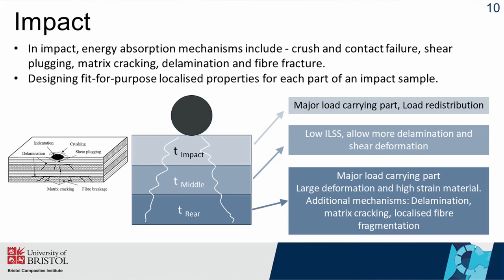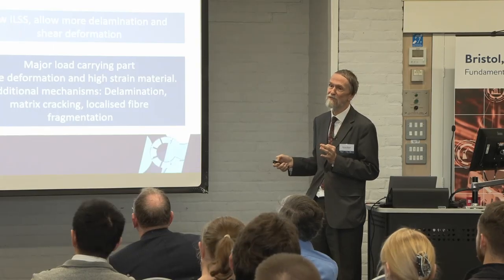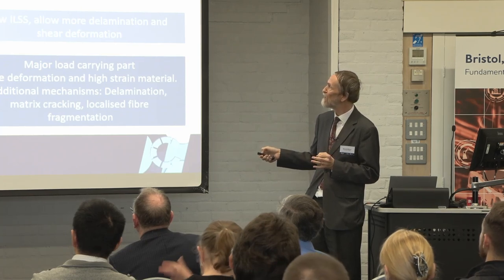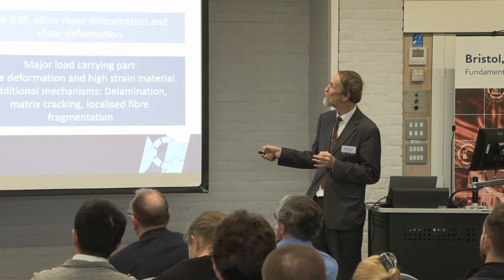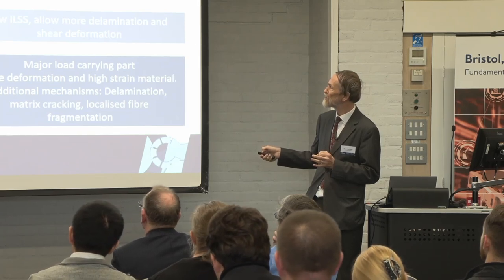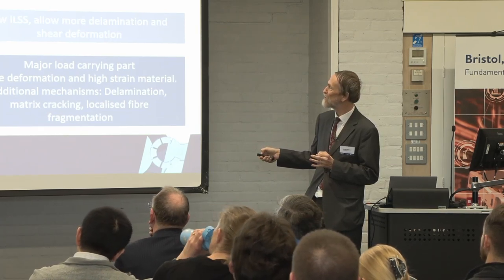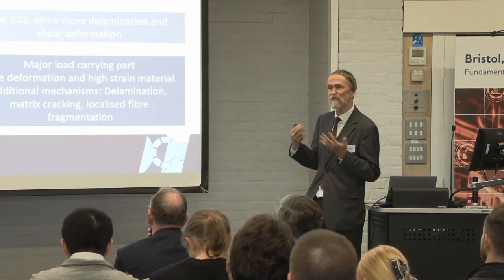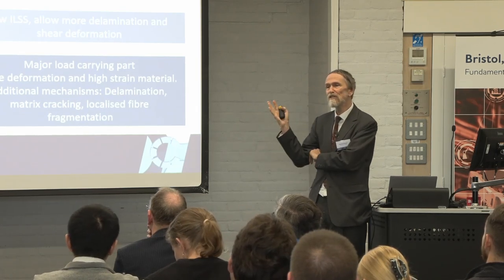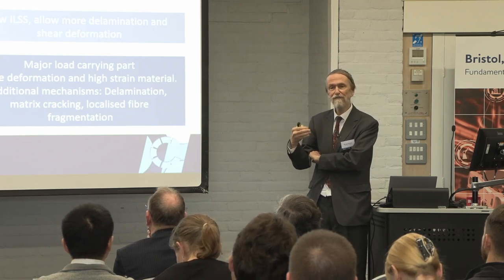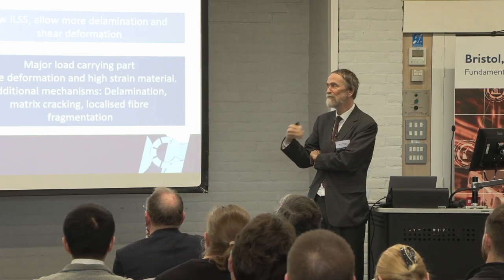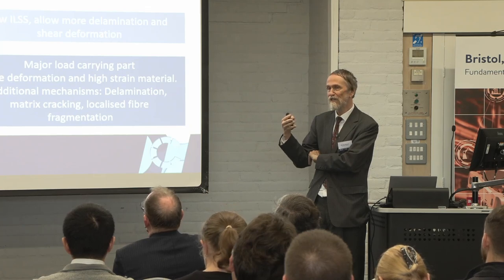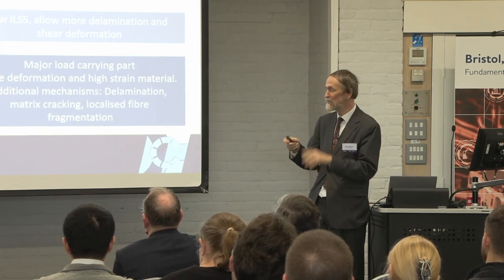So what about impact? This is a very complex problem. The mechanisms are really complicated and not really well understood despite all the work that's been done. We've got lots of different mechanisms, the energy absorption. We have local events that happen where we have contact and crush. We get shear failure, plugging, delamination, transverse cracking and fiber failure. It's all very, very complicated. What we've tried to do here is to look at the different aspects of that failure mechanism by trying to design laminates where we put different properties in different places.